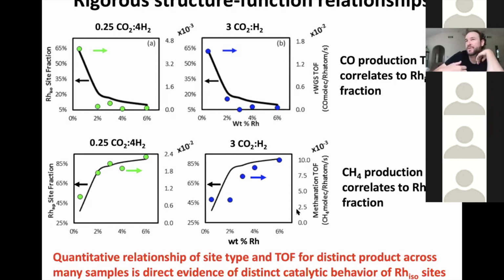So the behavior of any given catalyst really is just dictated by the fraction of sites that you have that are isolated compared to the fraction of sites that you have that are nanoparticles. And this will give you the overall selectivity you have for a rhodium catalyst. And this way we could develop a structure-function relationship.